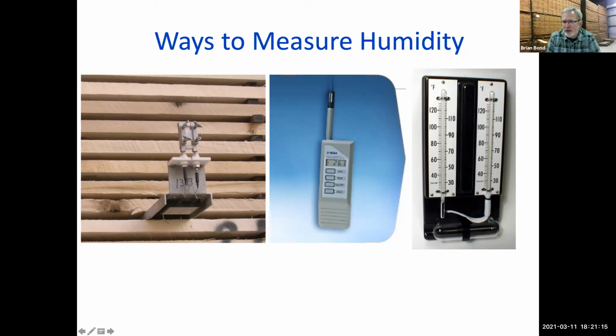There's water in this chamber right here. It keeps this wick wet. And the rate of evaporation creates a cooling effect on this thermometer. So this thermometer should always be less than what this thermometer is. So this would be the dry bulb, and the term for this would be wet bulb. And the difference between these two, you can look up in a chart and see what the relative humidity is. Or you can get fancy and get a digital meter. You can go from Walmart to Grainger's to anywhere online and find a relative humidity sensor if you want to go that way. But it's very important if you're drying lumber to be able to measure relative humidity and temperature in the drying environment if you want to make any kind of changes to what you're doing in the process.